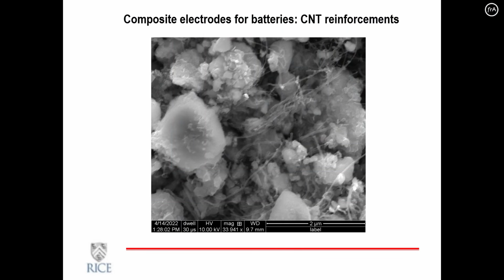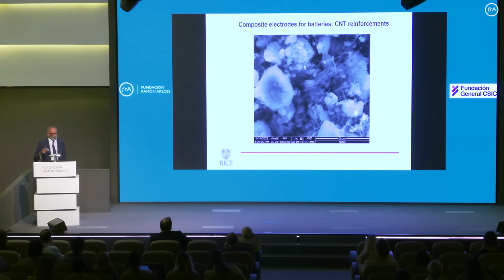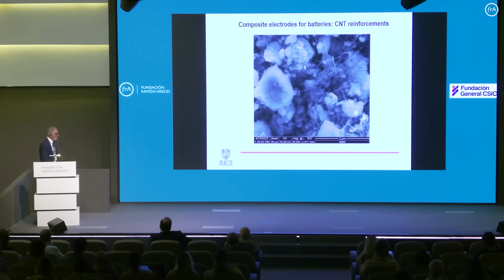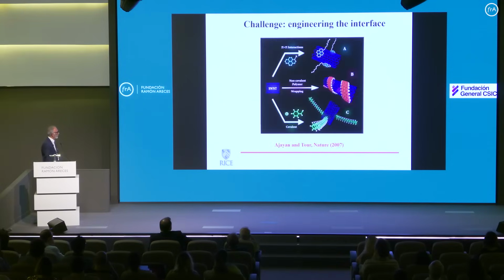So again, one of the big uses for graphene or nanotubes is in batteries, because by adding a small amount of these, you can get very high conductivity. Many of these electrode materials that people use are not conducting, so they need to add carbon to make them conducting. Either you can put just normal carbon, which means you'll have to put 25% of carbon, or you can put 3% of carbon nanotube and still get the conductivity that you need. So there are some advantages of these nanoscale high aspect ratio materials. So this is an interesting composite. It doesn't have to be ordered, but nevertheless, it's very useful.